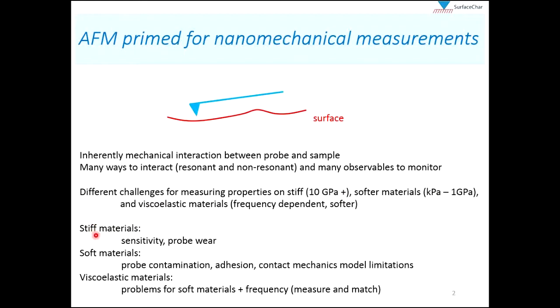So for stiff materials, some of the challenges that AFM faces include sensitivity. The cantilevers are actually fairly soft and compliant, and we can only make them so stiff. So often we just run into a wall in terms of how sensitive this cantilever can be on a stiff sample, unless you go to higher order modes. Also for stiff and especially hard samples, AFM can suffer from probe wear.